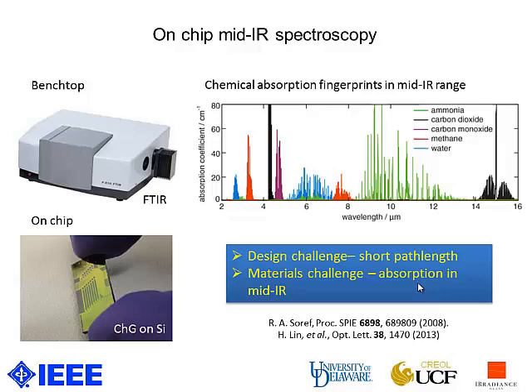The other problem is from material. Silica, one of the most common materials used for low-index undercladding, becomes opaque after 3.5 microns. This means the typical SOI platform for fabrication of photonic devices cannot be used for mid-infrared device fabrication. So we have to find other good materials for mid-infrared on-chip device fabrication.